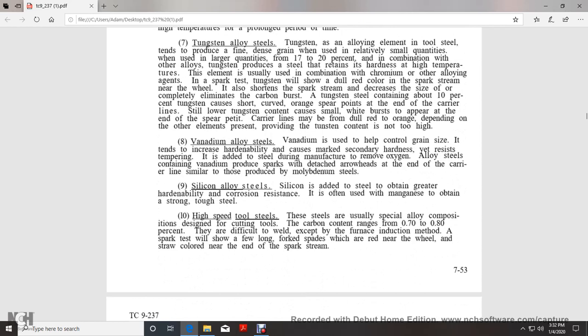Alright, tungsten alloy steels. Tungsten, an alloying element of tool steel, tends to produce a fine, dense grain when used in relatively small quantities. When used in large quantities, from 17 to 20% in combination with other alloys, tungsten produces steel that retains its hardness at high temperature. It is usually combined with chromium or other alloying agents. In a spark test, tungsten will show a dull red color in the spark stream near the wheel, but also shortens the spark stream, decreases its size, or completely eliminates the carbon burst.